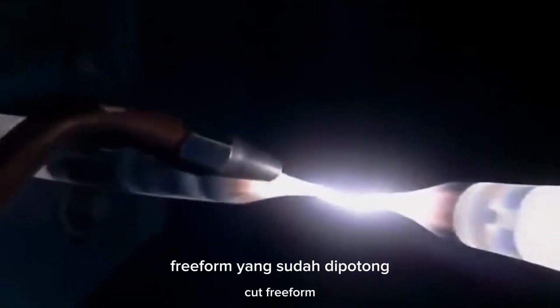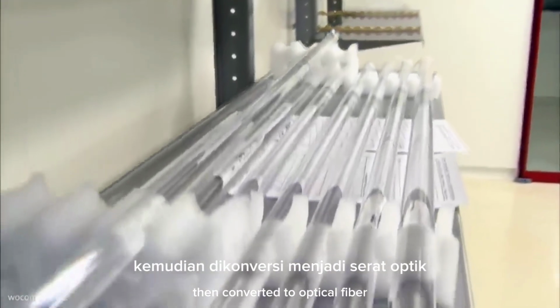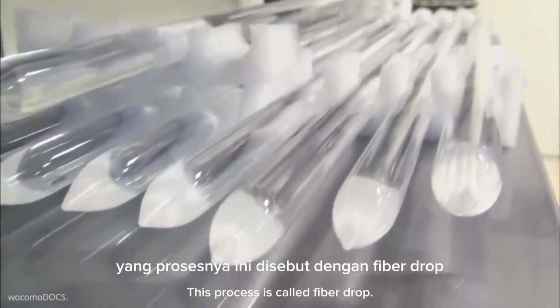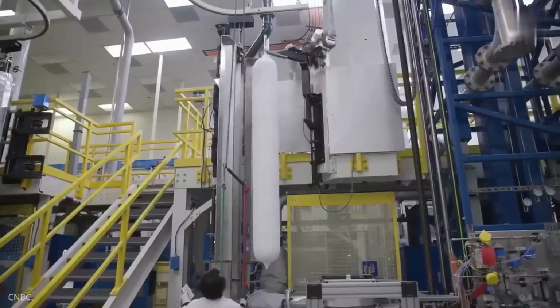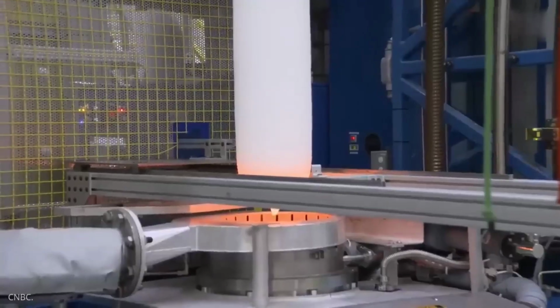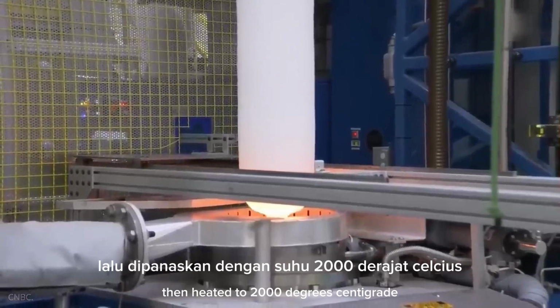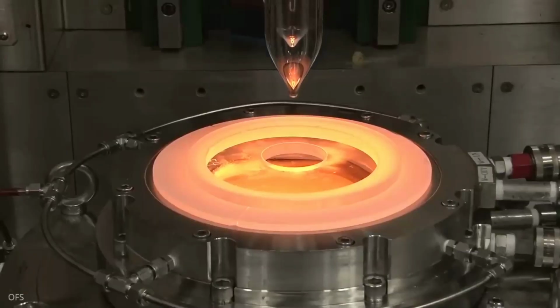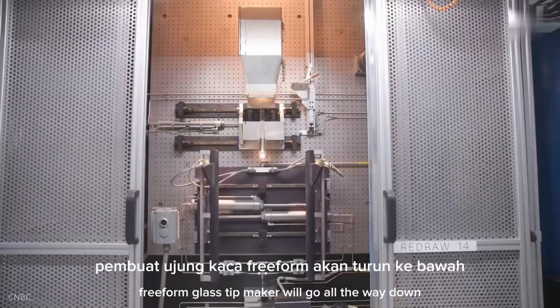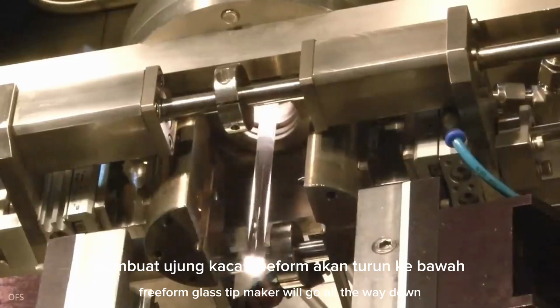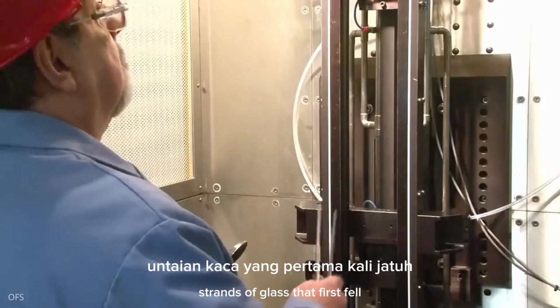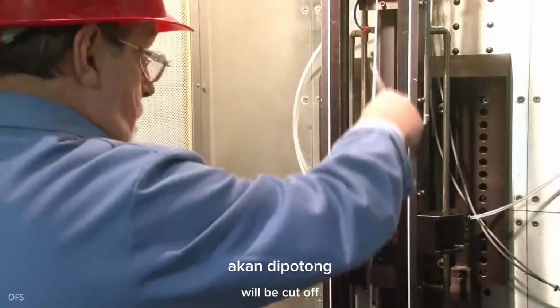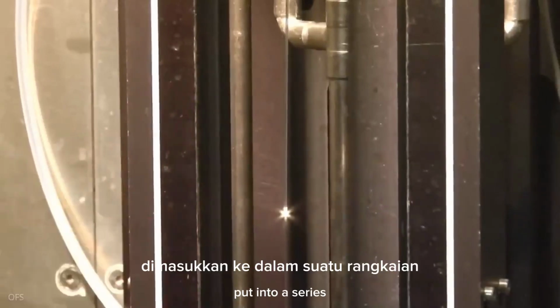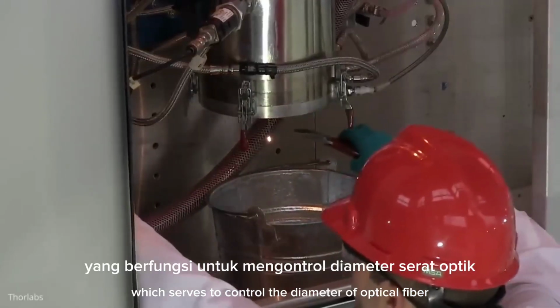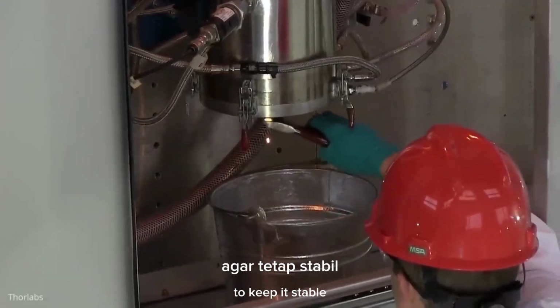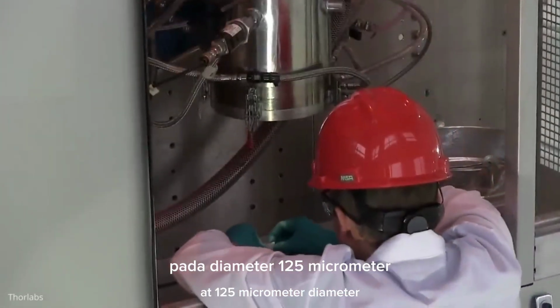Next, the cut preform is converted to optical fiber. This process is called fiber draw. The preform is inserted into a furnace, then heated to 2000 degrees centigrade to soften the end of the preform. Then, by gravitational force, the glass tip of the preform goes all the way down. The strands of glass that first fell are cut off. Then the remaining strand is put into a gauge, which serves to control the diameter of the optical fiber to keep it stable at 125 micrometers in diameter.